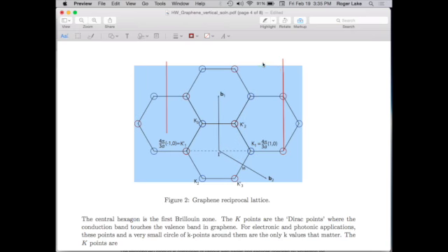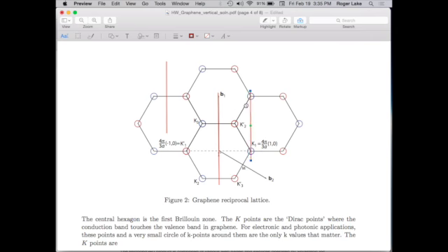So I might have 1 and 0, and I guess I'd need one to go through these K points here, and there'd be others. But if it goes through a K point, that means you go right through that point where they touch, and your carbon nanotube is metallic. If you roll it another way, you still have a discrete set of lines. They don't go through the K point, and now you've got a semiconducting tube.